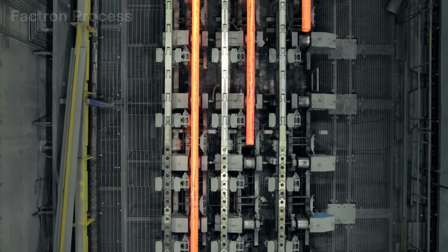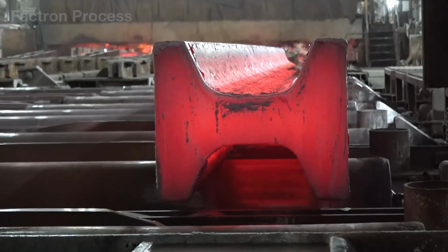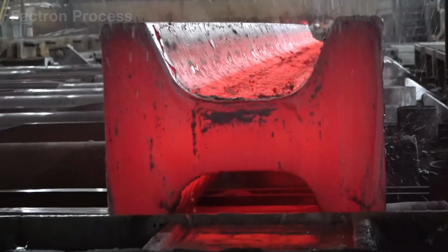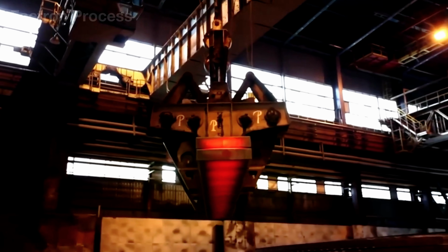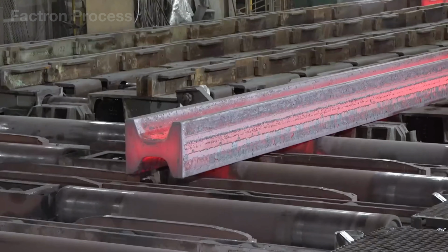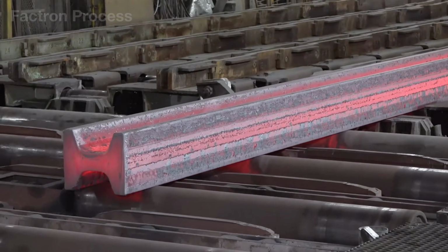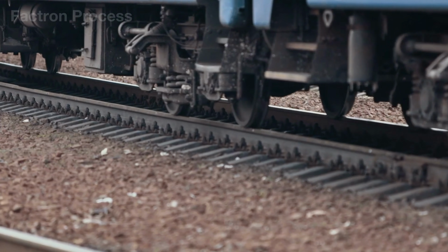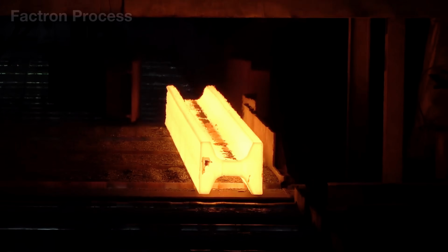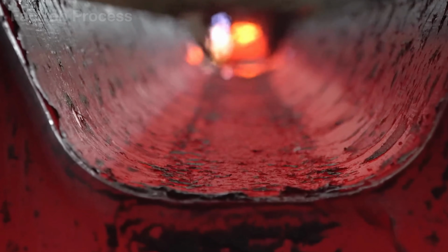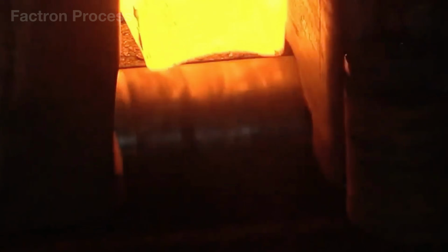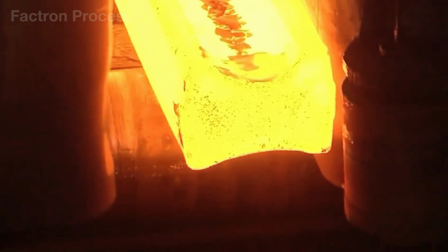Leaving the rolling stands, the rails are still glowing red and contain significant internal stresses. Standard rails are placed on cooling beds, where heat is released gradually to reduce warping and cracking. For rails intended for heavy haul freight lines or highly abrasive curves, the railhead then passes through an online heat treatment system. Compressed air jets or air-water mixtures cool only the running surface at a tightly controlled rate.